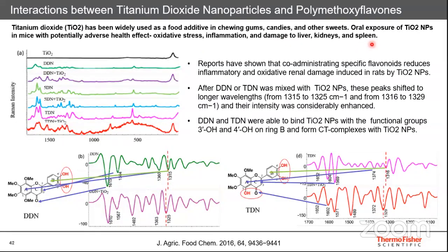Now, what they have observed is that when you add TiO2 along with other flavonoids, it reduces the damage, reduces the inflammatory effect, as well as the renal damage caused by the TiO2 material in that food material. But what they wanted to study was how the interaction works. What is causing that reduction of the adverse effect of TiO2 because of the presence of these flavonoids? That is why they did that study.